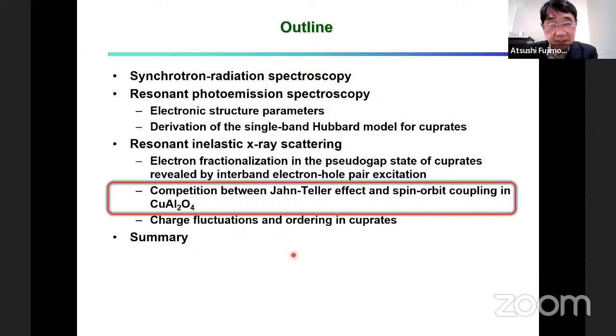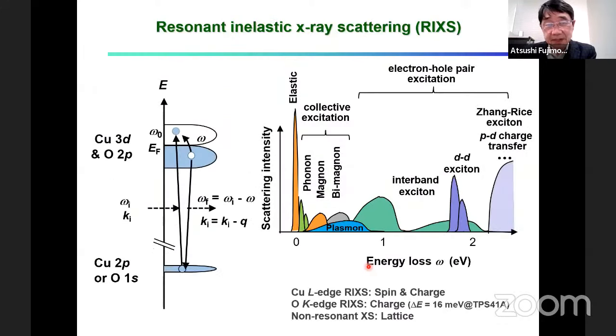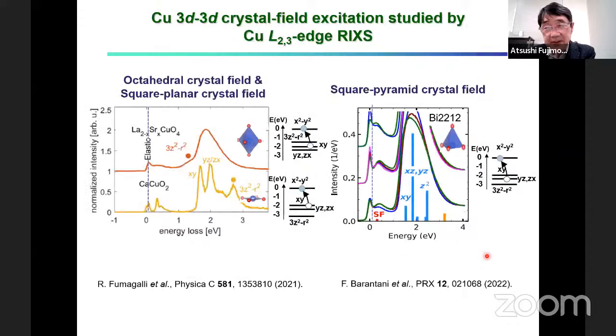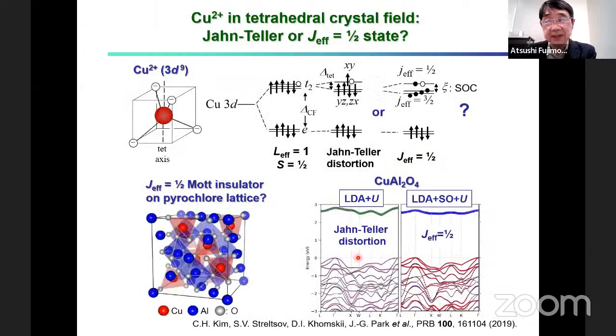Then let me go to this next topic. Now we focus on the DD excitation. DD exciton, as already mentioned for cuprates, is excitation between crystal field levels. But this can be applied to different copper oxide. This is an interesting material, copper aluminum O4, in the spinel structure, in the so-called pyrochlore lattice.